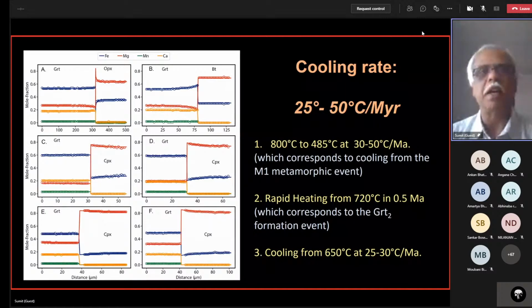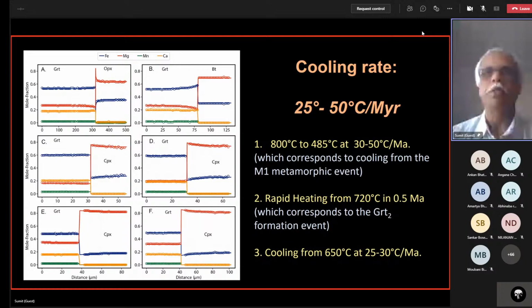And as you see now, there's the same picture really that you saw before, where you can fit all the profiles quite well. However, to do the whole thing, you need a more complex thermal history. So you need a 3-stage history. What you need is a cooling from 800 degrees to 485 or 480 degrees centigrade at that 30 to 50 degrees centigrade per million years.